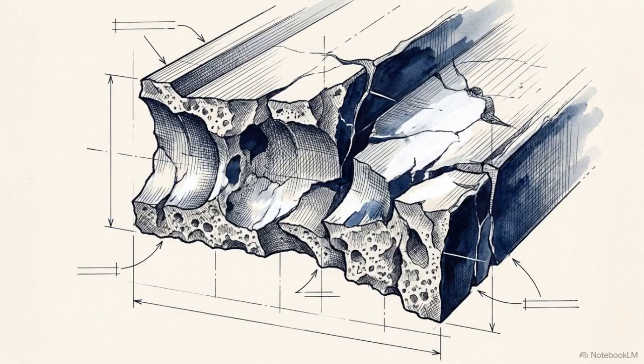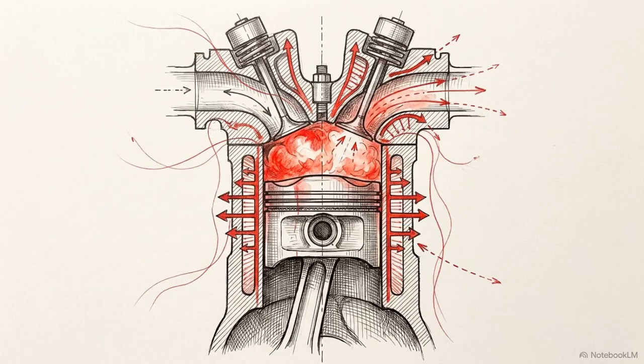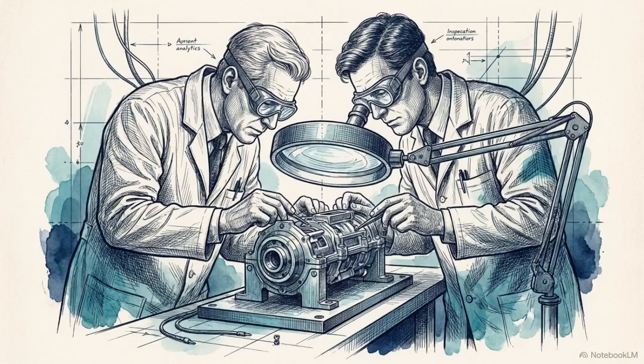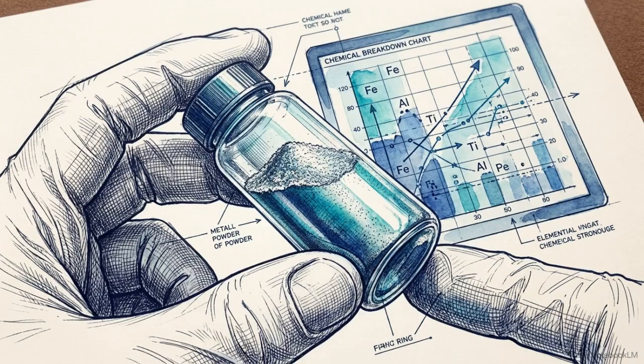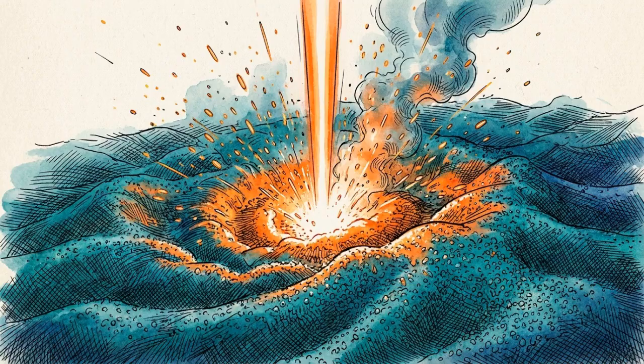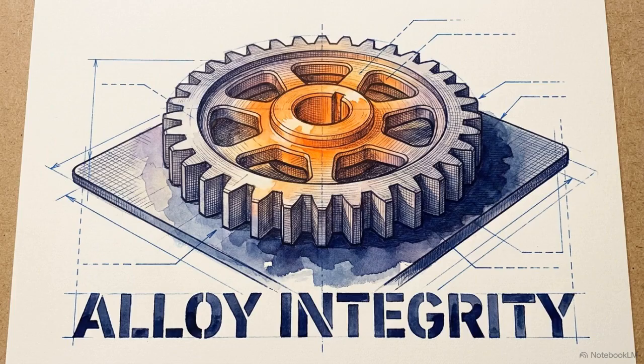Cautionary: additive manufacturing introduces a severe risk if not tightly controlled. Standard 3D printed metals lack the yield strength required to survive the extreme forces of an F1 combustion cycle. Red Bull Powertrains counters this through rigorous technical control, tracking the exact provenance and chemical composition of every batch of raw metal powder before it enters the printer. During the print, parameters like laser hatching and layer thickness are minutely tuned to ensure the mechanical properties of the alloy aren't compromised during fusion.